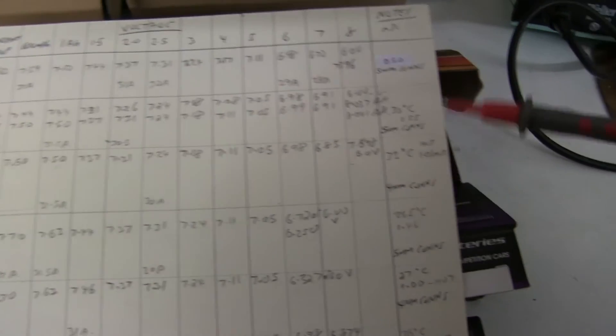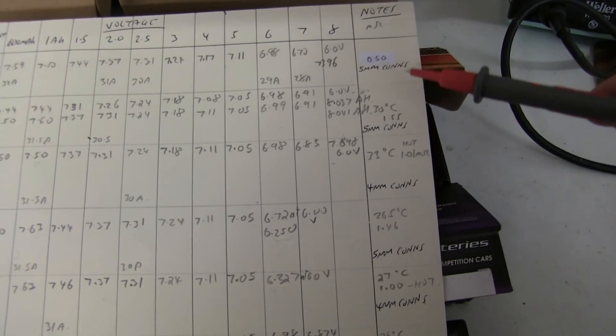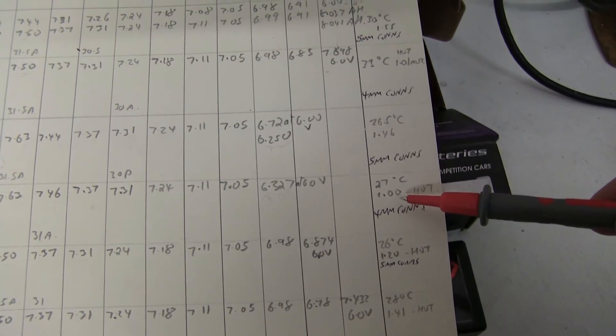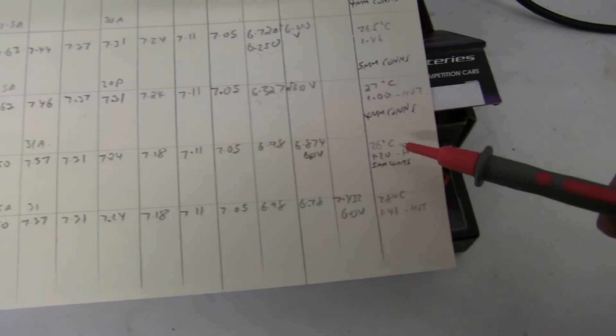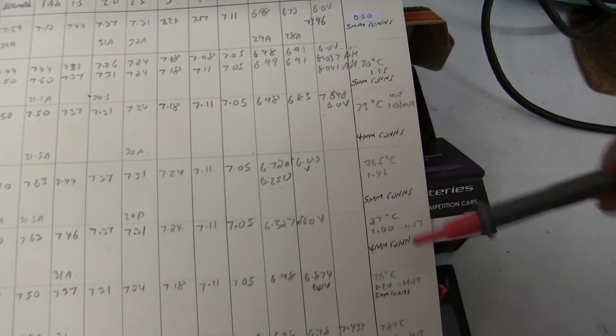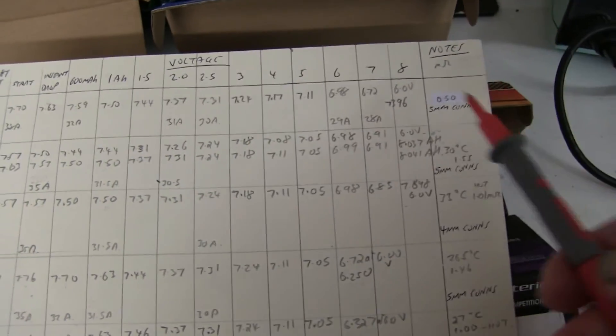I also tested some of the internal resistances on these batteries after discharging when they're hot and I've also tested some when they're ambient. I don't find it's a totally accurate indicator of performance. For instance, the Phantom and the Aromax, the Aromax was one milliohm when hot which is pretty good figure. The Nanotech Ultimate 66 was 1.2 when hot and the graphene was only 1.41. So it's quite difficult to measure the IR when it's really really low. I did get a figure of 0.5 on the IR and I checked it a few times, it's very very low, but it didn't really make any difference to the voltage as it was discharged.